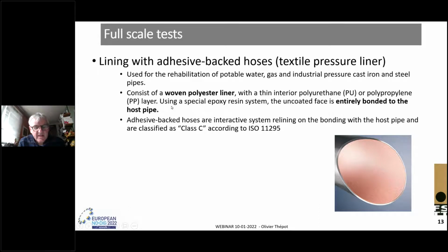The liner tested was an adhesive backed hose, a textile pressure liner, habitually used for the rehabilitation of potable water, gas, and industrial pressure cast iron and steel pipes. It consists of a woven polyester liner with a thin interior polyurethane or polypropylene layer. Using a special epoxy resin system, the uncoated face is entirely bonded to the host pipe. Adhesive backed hoses are an interactive system